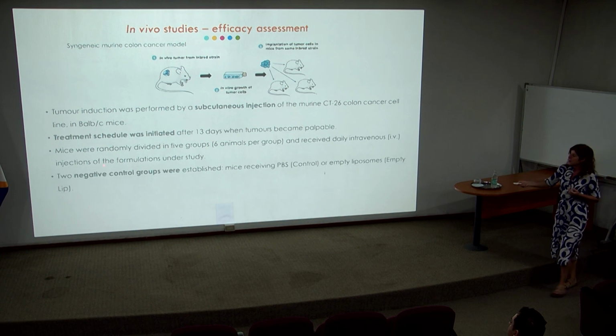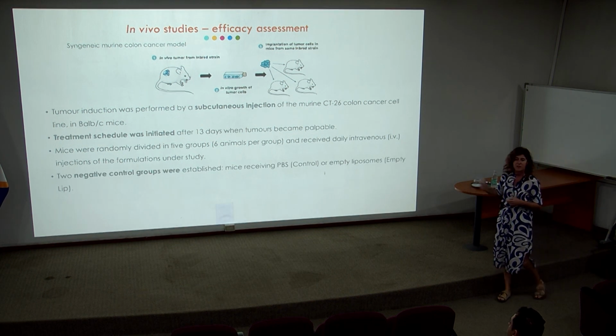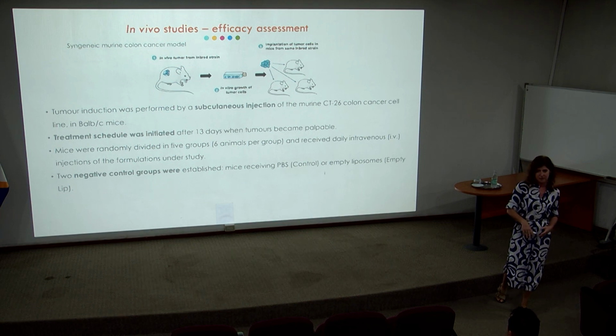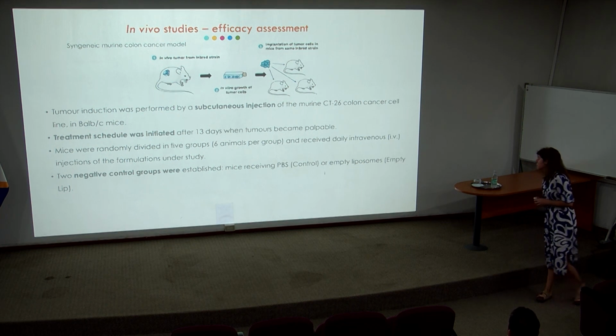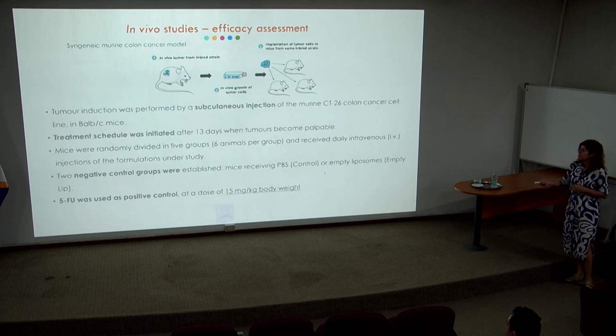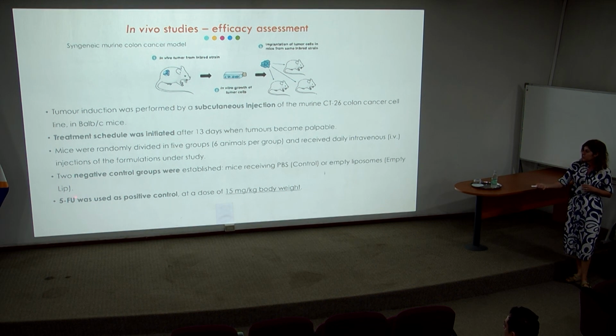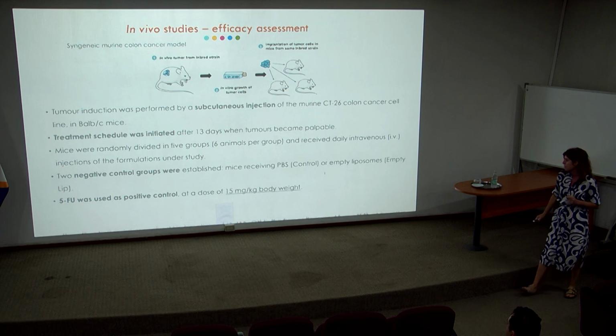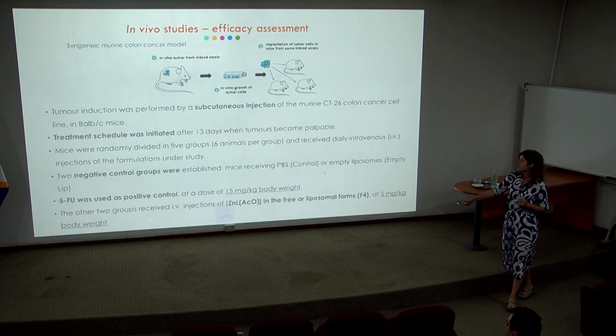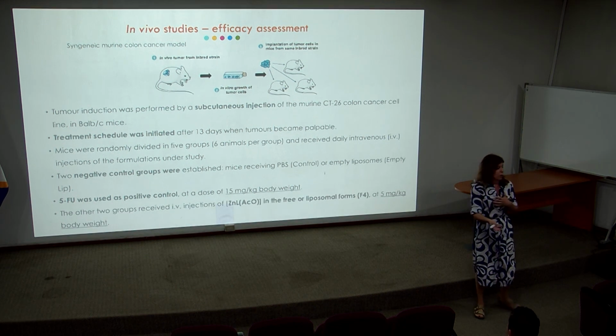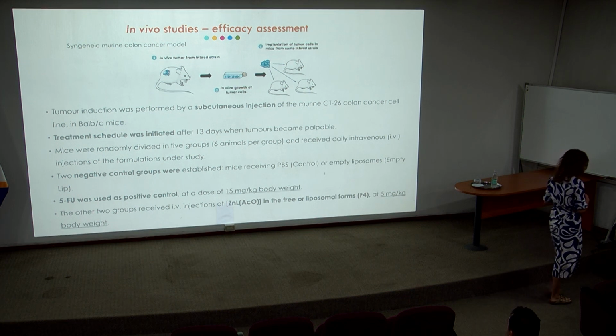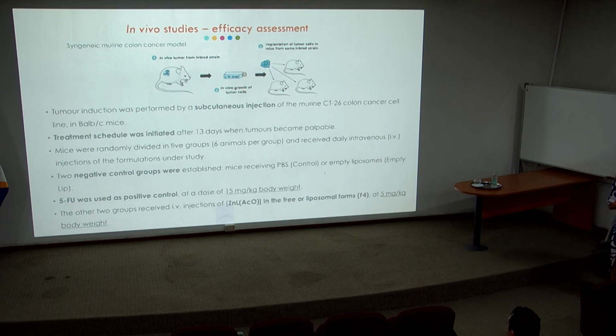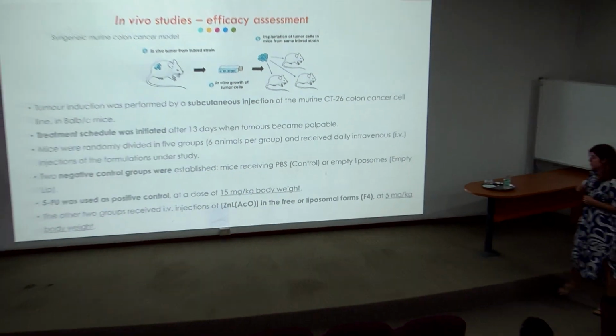So we had 2 negative control groups, mice that just received PBS or empty liposomes. And the positive control was 5-fluorouracil. This was the dose, 15 milligrams per kilogram of body weight. And the other 2 groups received either the complex in the free form or in the liposomal formulation at a lower dose, 3 times lower, 5 milligrams per kilogram.